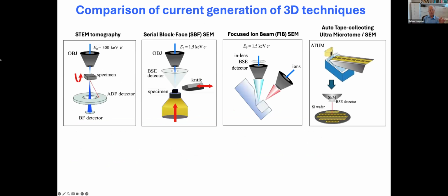look at this here. These are just simplified schematic diagrams of the techniques that we've used. In STEM tomography, we focus an electron probe into a thick specimen and tilt it and obtain an axial bright field detector signal, which is not what you typically do in STEM, but this is what works well for looking at thicker sections. And that can give us 3D information.